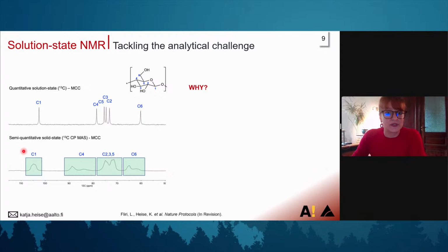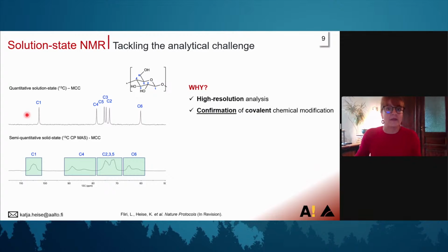So what we observe is that we don't have proper resolution of all cellulose backbone signals, and we also have peak broadening. If we use now our ionic liquid electrolyte, we can do solution state NMR. We have well-resolved spectra, and we also have quantitative information. So yeah, we use it for high resolution analysis.